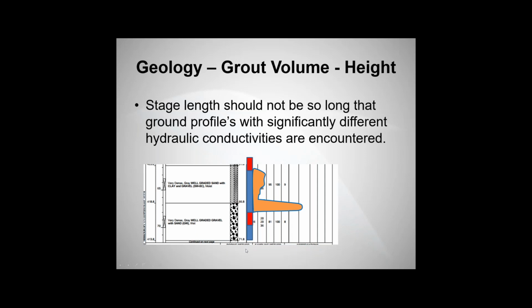The example that I show here is just a boring log that I pulled from somewhere. There's a grout hole, which is indicated by this blue line, and the stage, the grout zone, is between two packers, which are indicated by the red spots in this grout hole. So the zone in between those two red spots is what we're grouting. As you can see, the lower portion of that zone is a gravel, and the upper portion is sand. I didn't have the data on this, but just to prove the point, the assumption is that the gravel has a much higher hydraulic conductivity or permeability than the sand does. And so the orange over here indicates a potential spread of the grout.